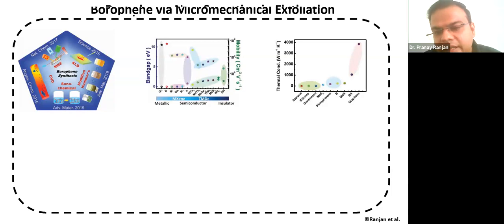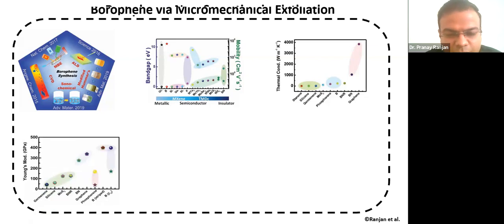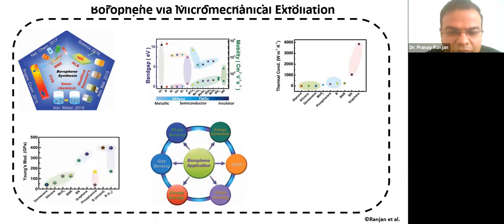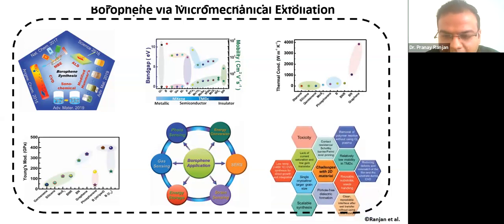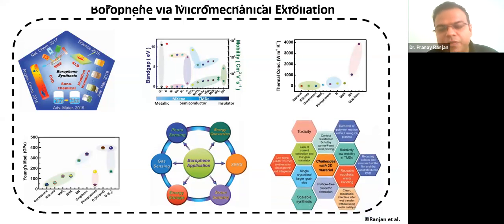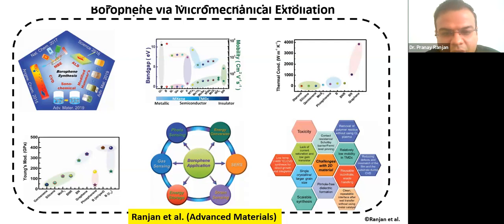However, it's comparable to boron nitride at some stage, or phosphorene. Then Young's modulus, we found that this material is the best among all classes of 2D materials, and we tried to find out different applications of Borophene in different areas like photosensing, energy conversion, strain sensing, energy storage, and gas sensing. And we tried to summarize all the challenges which 2D materials get before ending up with the device. So these are basically at the lab scale we tried to summarize and publish.